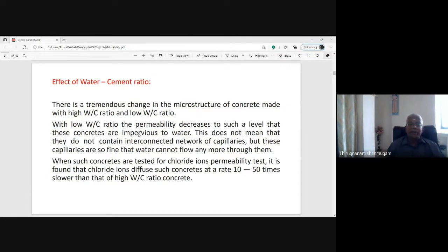But at the same time, if the water cement ratio exceeds 0.5 or 0.6, etc., a higher water cement ratio, then the microstructure of the concrete exhibits a lot of voids in between the ingredients of the concrete, and porous action will be there, etc. And the harmful ingredients from the atmosphere can easily penetrate through the concrete and affect it, causing carbonation of concrete, chloride ingress or sulfate attack of the concrete, etc. And finally, it causes the deterioration of the concrete.